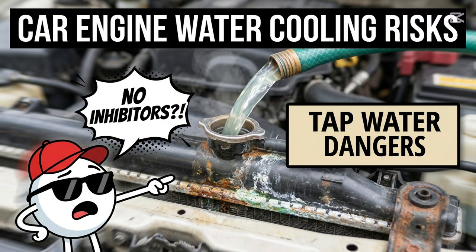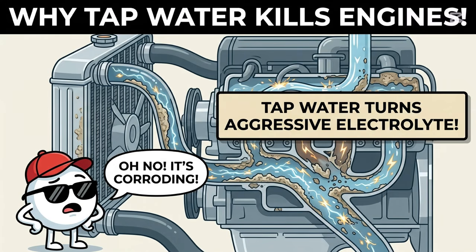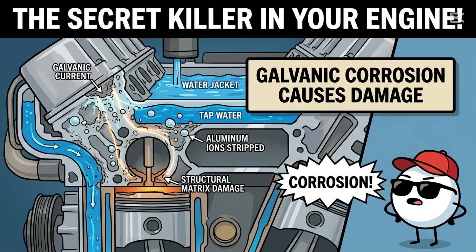Tap water has zero, literally none, of those protective inhibitors. What it does have instead is a cocktail of dissolved minerals, calcium, magnesium, chlorides, sometimes silicates from the treatment process itself. All of that turns plain tap water into what's essentially an aggressive electrolyte, a fluid that's actually better at conducting galvanic current than distilled or engineered coolant would be. The moment tap water fills those cooling jackets, a microscopic but very real galvanic current begins flowing from the more active metal, typically the aluminum cylinder head, toward the less active metal, stripping aluminum ions directly out of the structural matrix of the part.